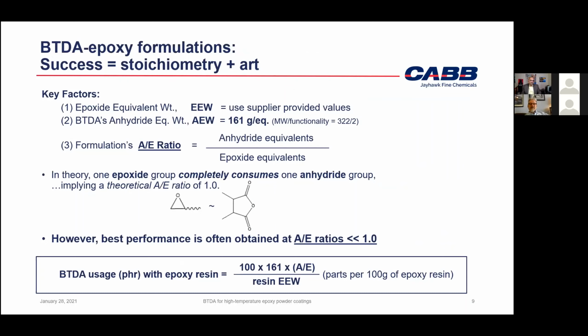Yeah, exactly. So the art of formulation really comes into play in BTDA-based epoxy formulations. And like Kevin has hinted, we did have to go off stoichiometry, if you will, in order to get better results. And we know from our historical experience that our customer base also uses far more off-ratio formulations for these kinds of systems. So basically, at the bottom, there is an equation. Different people calculate the usage rates of curing agents in different ways.